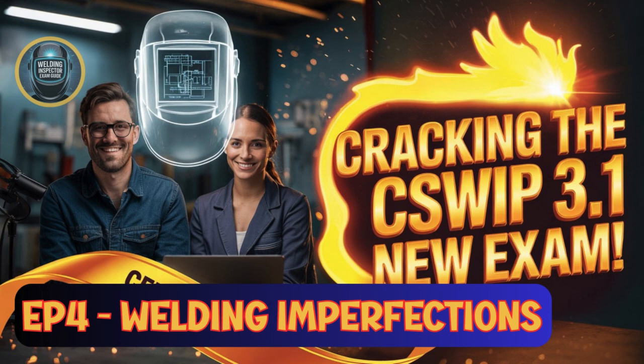And surface porosity then is just a gas pore that happens to break through the outer surface of the weld. Precisely. It's a gas pore that manifests right on the weld surface. The causes are very similar to general porosity: damp or contaminated surfaces, maybe low fluxing activity in the process, excess sulfur in the material, or loss of the shielding gas protection due to things like too long an arc or external drafts blowing the shield away.